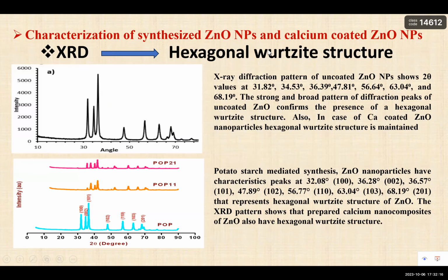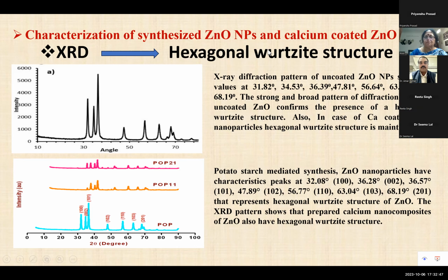Now, for characterization of the synthesized zinc oxide nanoparticles, various techniques were used. The first one is XRD. The X-ray diffraction pattern of uncoated zinc oxide nanoparticles shows 2 theta values at 31.8 to 34. The strong and broad diffraction peaks of uncoated zinc oxide nanoparticles confirm the presence of a hexagonal wurtzite structure. Also, in the case of calcium-coated zinc oxide nanoparticles, the hexagonal wurtzite structure is maintained. In another study, we did potato starch-mediated synthesis of zinc oxide nanoparticles. Again, the hexagonal wurtzite structure of zinc oxide nanoparticles is maintained.